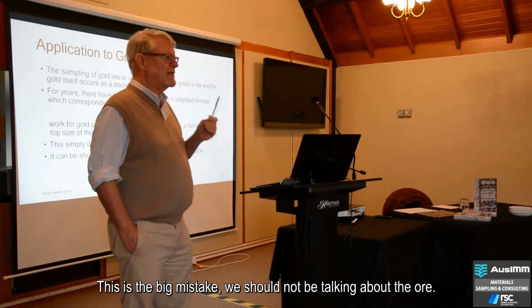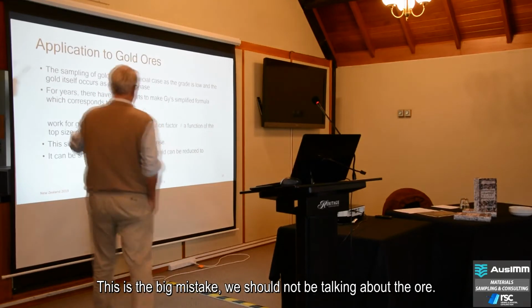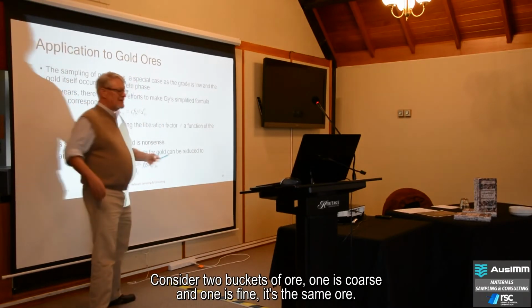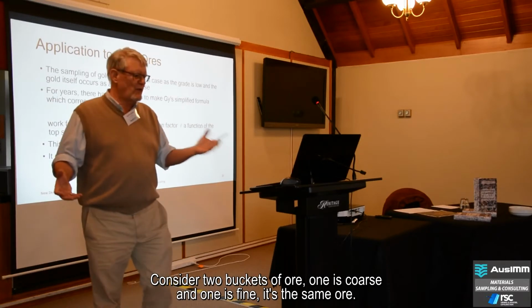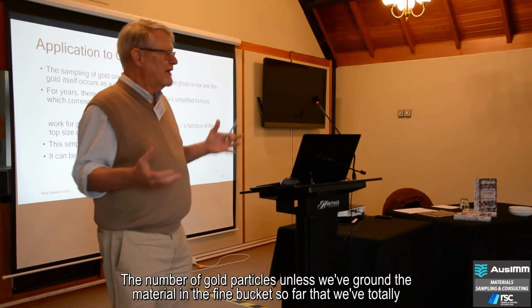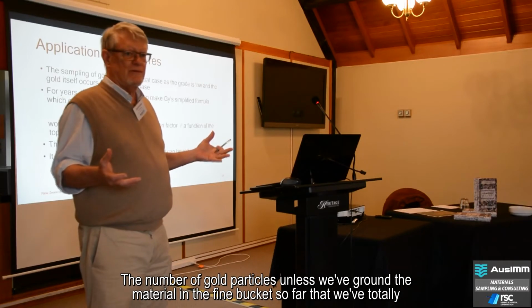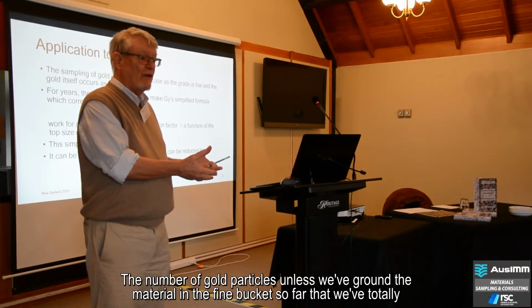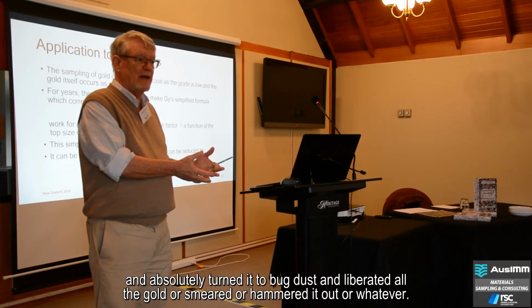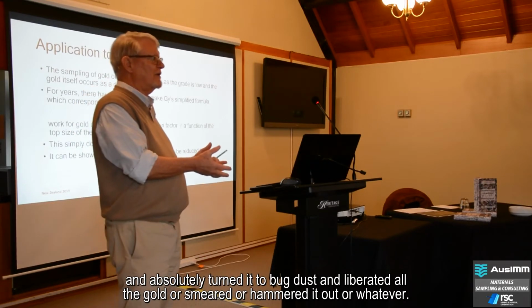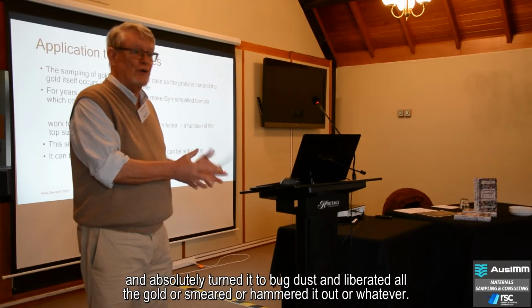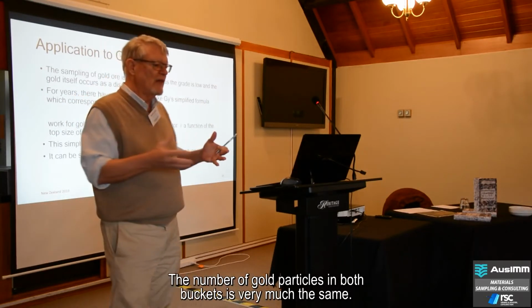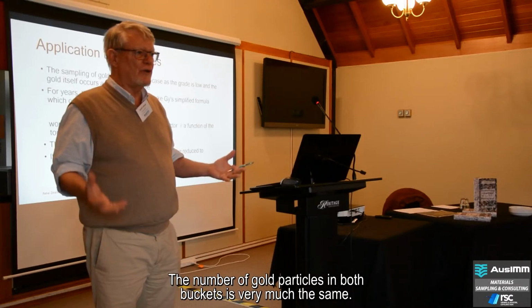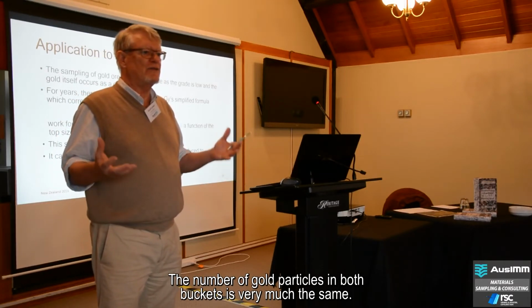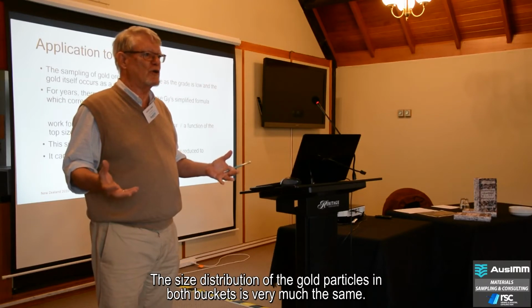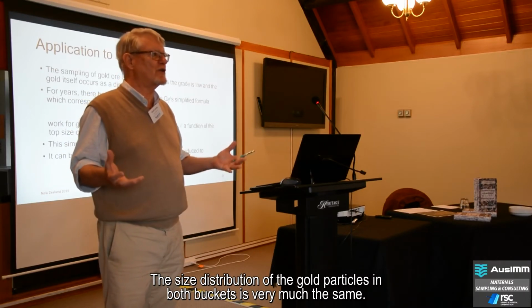And this is the big mistake. We should not be talking about the ore. Consider two buckets of ore. One is coarse and one is fine. It's the same ore. The number of gold particles, unless we've ground the material in the fine bucket so far that we've totally and absolutely turned it to bug dust and liberated all the gold or smeared it or hammered it out or whatever, the number of gold particles in both buckets is very much the same. The size distribution of the gold particles in both buckets is very much the same.